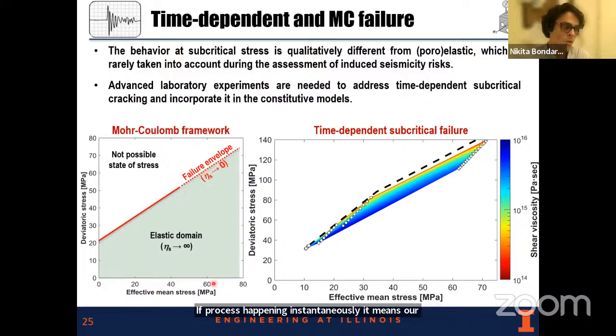At the same time, below the failure envelope, we have an elastic domain where there is no time-dependent response, or all these processes are infinitely slow, meaning infinite viscosity. As soon as we reach this failure envelope, the material magically switches between these two types of responses. It's a convenient model, but it's not fully representative of the process happening.